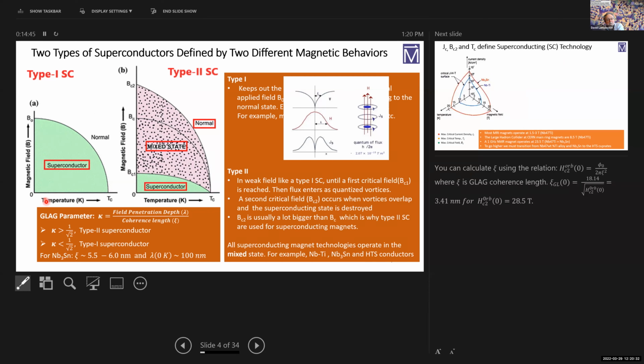Coming out of the Ginzburg-Landau theory is this parameter kappa, which is the ratio of the field penetration depth to the coherence length. And he said, well, if kappa is less than 1 over root 2, it's a type 1 superconductor. If it's greater than 1 over root 2, it's a type 2 superconductor. But in the paper, he said, well, this is just a mathematical solution. It has no physical meaning.